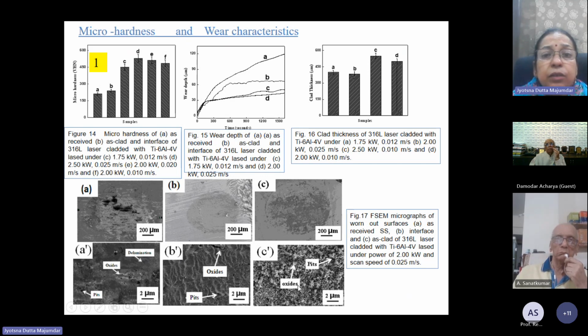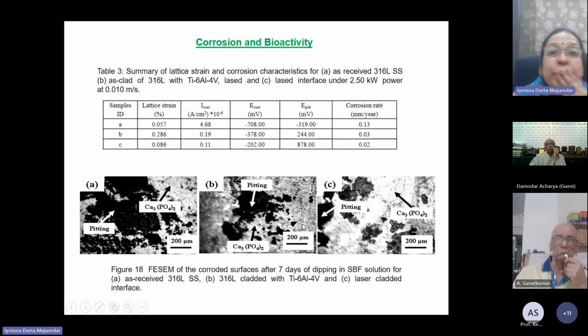When we examined corrosion resistance, that property was also improved in the case of titanium. Here A is as received, B is the as-clad Ti6Al4V, and C is the laser-clad interface. In all three cases we find that at the interface also the corrosion rate was quite low. At the interface we assumed that there would possibly be galvanic attack and hence the corrosion rate would deteriorate, but it was not so.